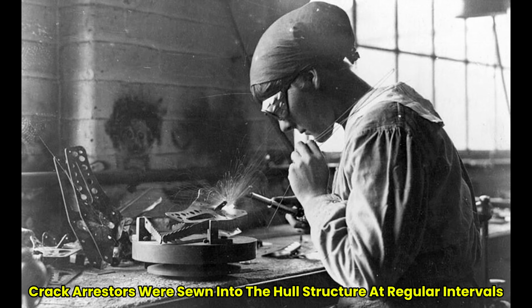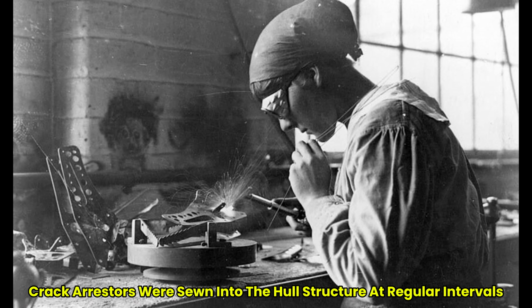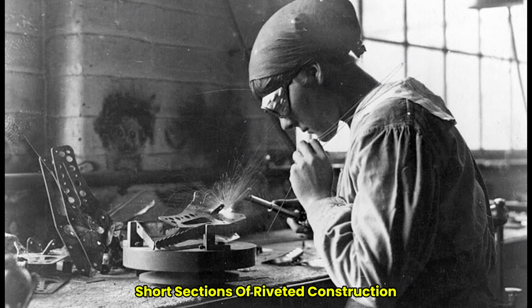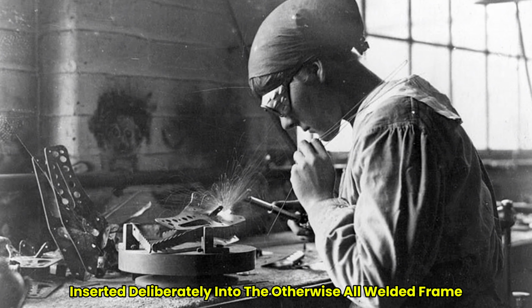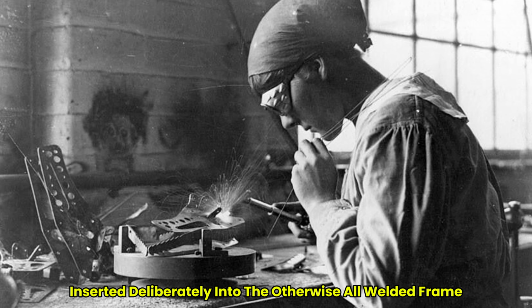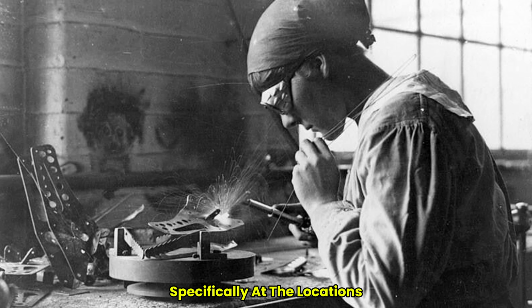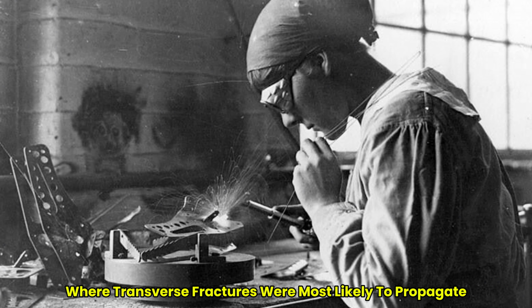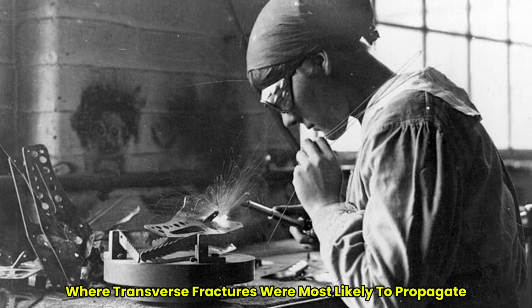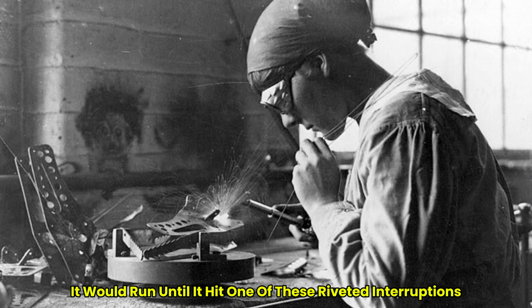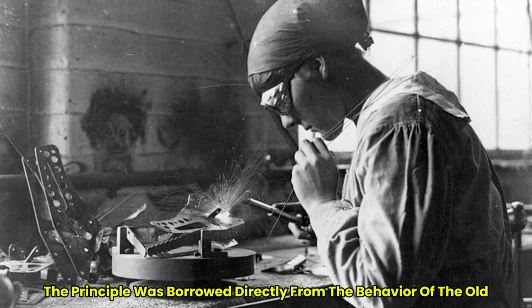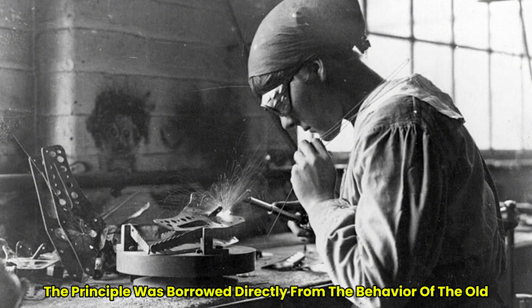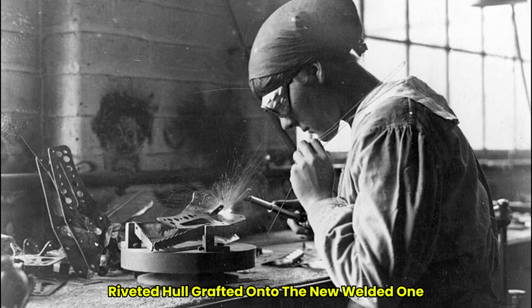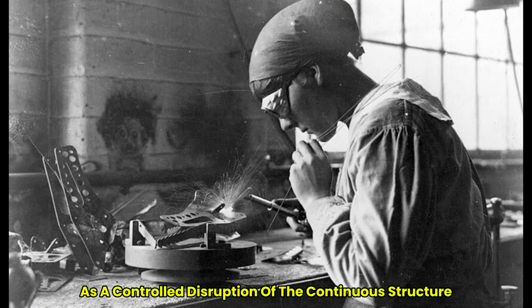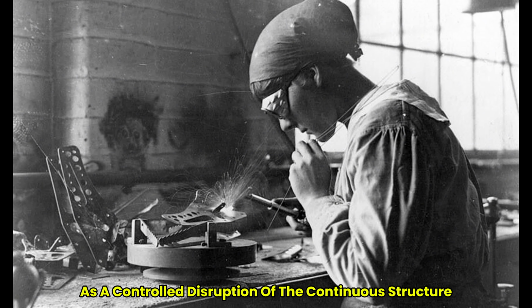Crack arrestors were sewn into the hull structure at regular intervals. Short sections of riveted construction inserted deliberately into the otherwise all-welded frame, specifically at the locations where transverse fractures were most likely to propagate. If a weld cracked, it would run until it hit one of these riveted interruptions, and there it would stop. The principle was borrowed directly from the behavior of the old riveted hull, grafted onto the new welded one as a controlled disruption of the continuous structure.